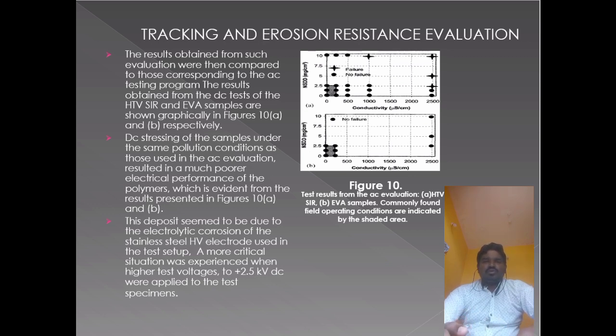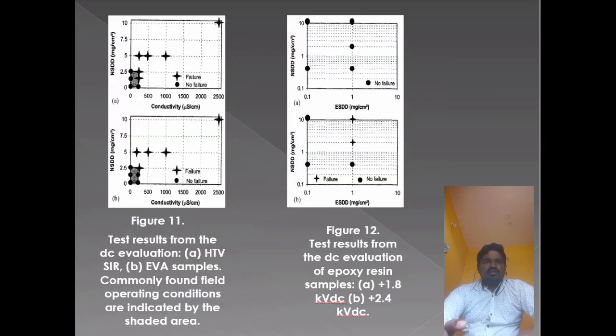For comparison purposes, the results obtained previously from the AC evaluation of these polymers are also included in figures 10A and 10B. As observed in figure 10A, during the AC evaluation of the HTV SIR samples, failures were observed only at very high pollution and conductivity levels. As also illustrated in figure 10A, these pollution levels are far higher than the most frequently found during actual field operation. Nevertheless, DC stressing of the samples under the same pollution conditions as those used in the AC evaluation resulted